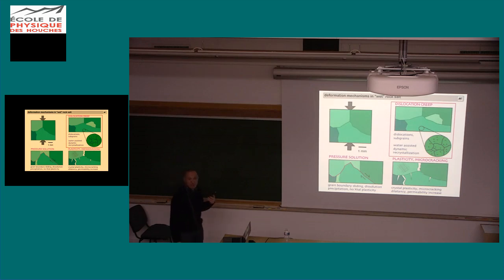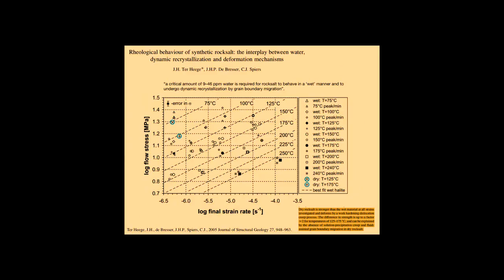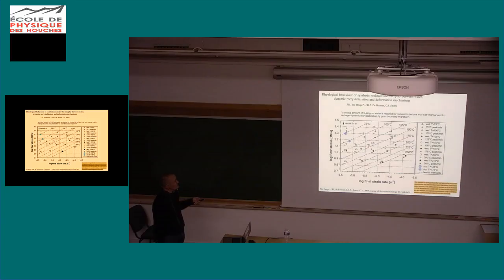And this was taken up in the laboratory of Chris Spiers, and there were quite a lot of important studies there. This is the paper by Jan ter Heege about his PhD, where he has done wet salt experiments at 75 to 250 degrees C, lots and lots of experiments with different strain rate and different flow stress, and he found this dislocation creep power law relationship.